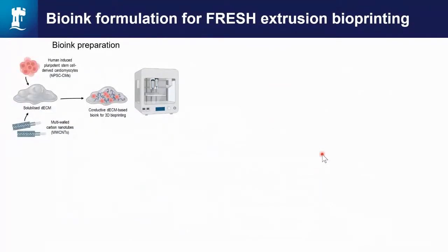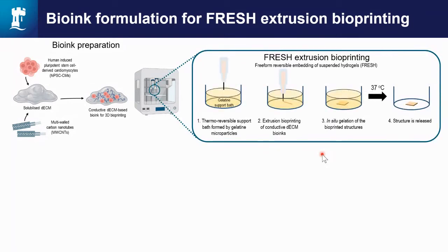Regarding the ink preparation, we solubilized these extracellular matrices, and we combined them with human induced pluripotent stem cell-derived cardiomyocytes, and also multi-walled carbon nanotubes, which in our case act as conductive nanofillers and increase the conductivity of our materials. Once we formulate our inks, we process them using a bioprinter. The technique that we use for bioprinting is called FRESH extrusion bioprinting. FRESH stands for freeform reversible embedding of suspended hydrogels. The main difference between FRESH and conventional extrusion bioprinting is that in our case, we print our materials inside a gelatin support bath.